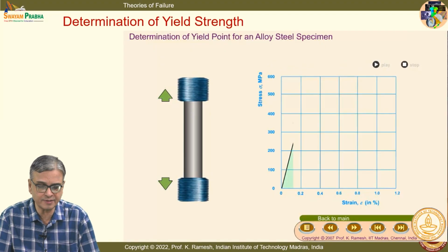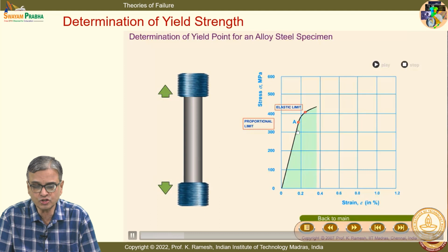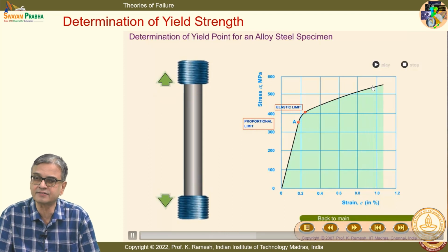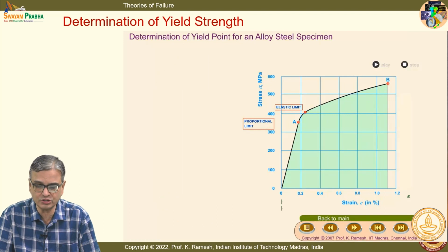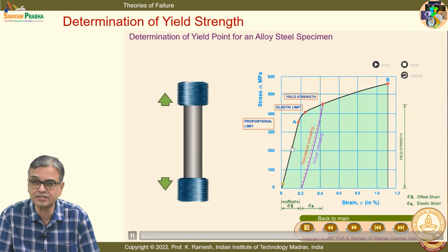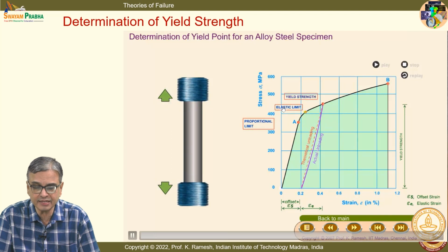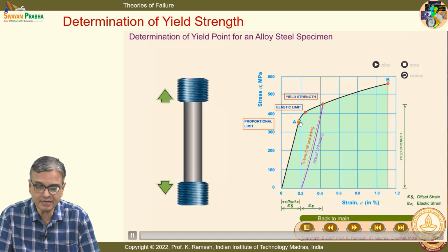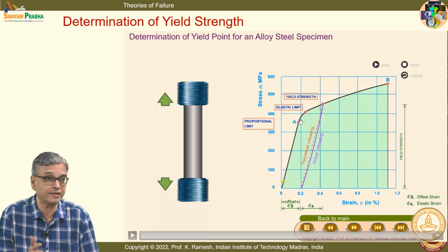And as I said, suppose I have an alloy steel which does not show any sharp change to identify the yield strength. You have a nonlinear curve like this. The recommended practice from codes is you take an offset strain of 0.2%, draw a line parallel to the initial slope, and wherever it meets the curve, this value is taken as the yield strength. And you also have a very marked point A and another point which is the elastic limit. The relationship is linear up to A. From A to the elastic limit, it can be non-linear. Fine.